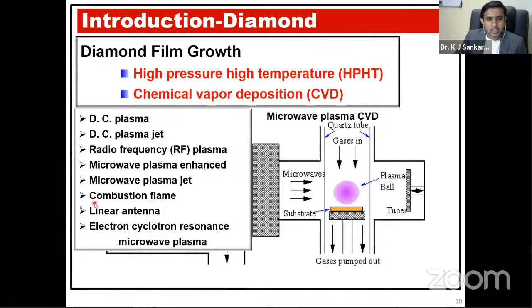One thing I want to focus on is the linear antenna CVD. This linear antenna CVD is a recently made CVD that came in 2015, and we can grow diamond films as big as a pizza. If you have a big 8-inch silicon wafer, we can achieve a very uniform diamond film using this linear antenna system. The system looks like a pizza machine, and we can put in a pizza tray, that is your substrate, and get a very nice diamond pizza formed as a diamond film on your silicon substrate. So this is the more advantageous microwave plasma CVD, recently made by the experts.